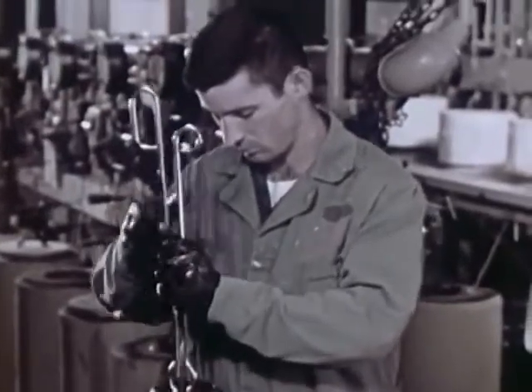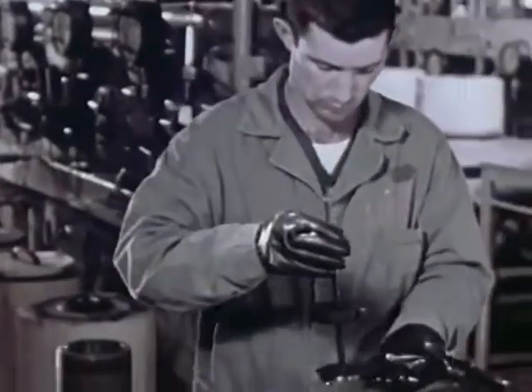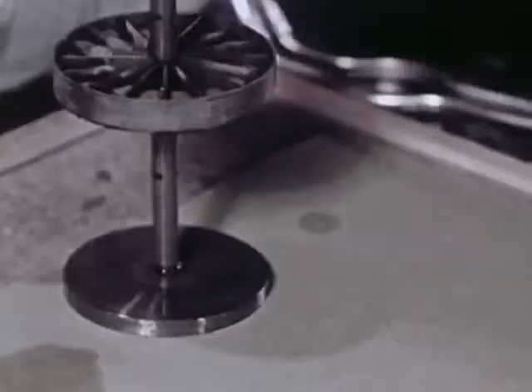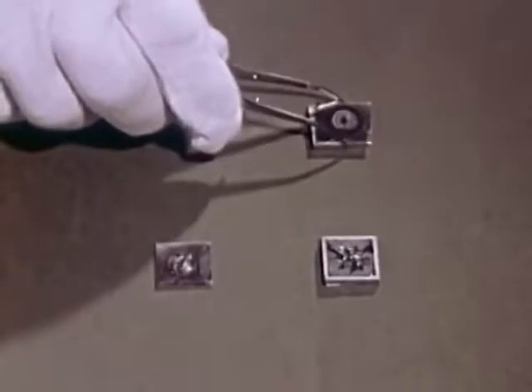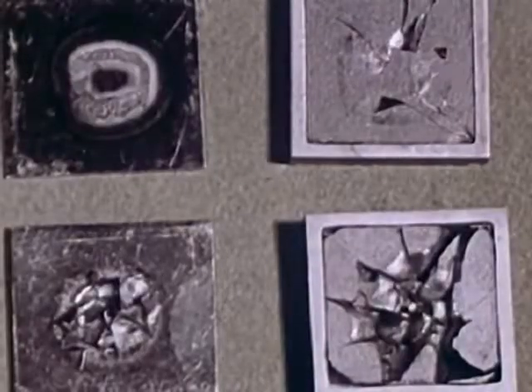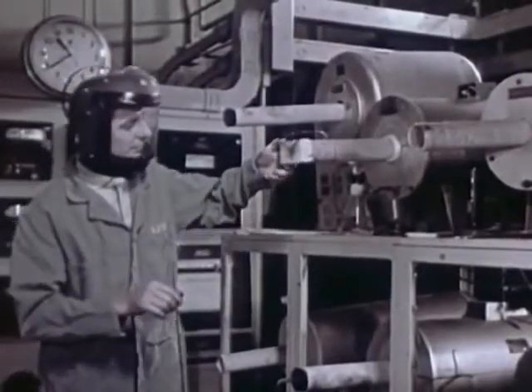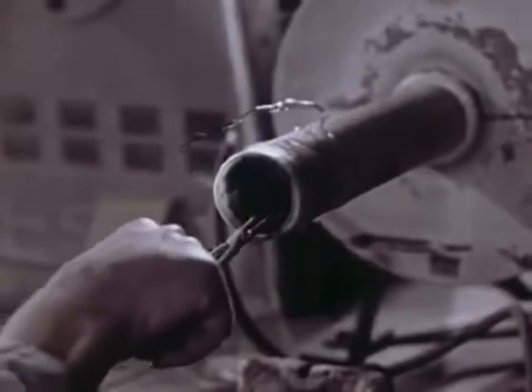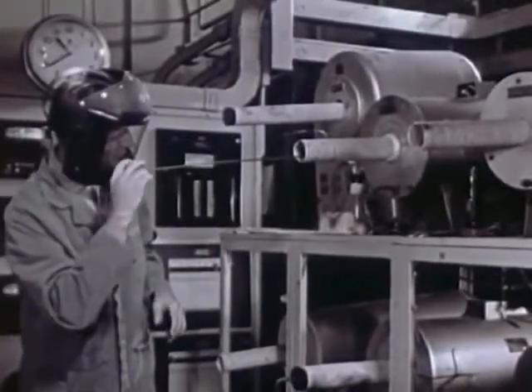Many aspects of the chemical behavior of the oxide were studied. These included such things as its reaction with hot water, its reaction with a zirconium alloy, which might be used as cladding, and the effects of particle sizes on chemical behavior. It was found that UO2 could be sintered successfully if carried out in a hydrogen atmosphere. This process increased both density and strength.